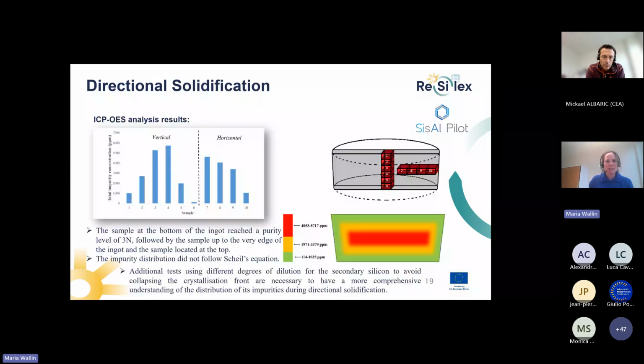And surprisingly, and as Mickael also saw when we sent it to him, it was not so pure. We reached only 3N. And the purest part was at the bottom and at the top and the side. So there was more dirt in the middle. And the theory was that it should be less pure at the top. So we got something else. So this method didn't work very well for us.